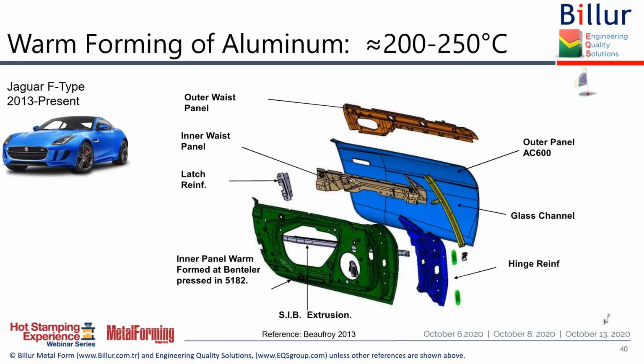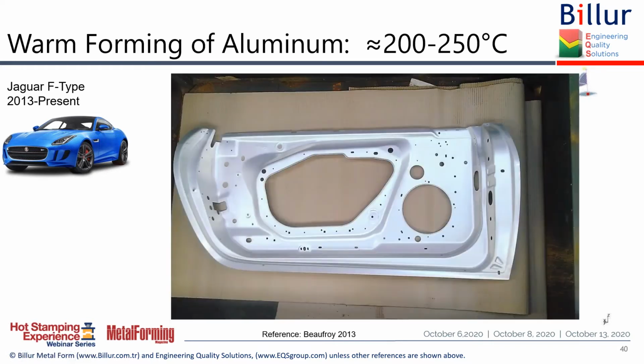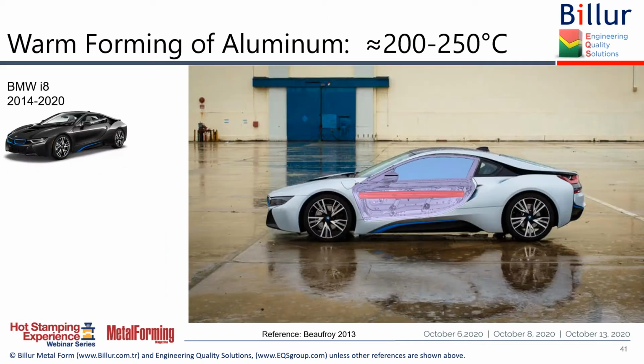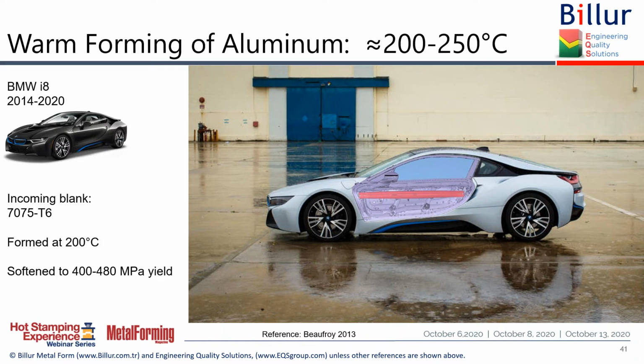So one of the first applications of warm forming of aluminum was done at Jaguar F-Type. It's still in production. The door inner of this car is deeper than 165 millimeters. In the previous version, it was an assembly of cast parts and sheets and etc. But in the new one, it's a single piece warm formed part at around 200 to 250 degrees. Another warm forming application was BMW i8. The door beam of this car was 7075 T6 as the incoming blank, but its heat treatment is slightly deteriorated to 400 to 480 megapascal yield. It's softened.